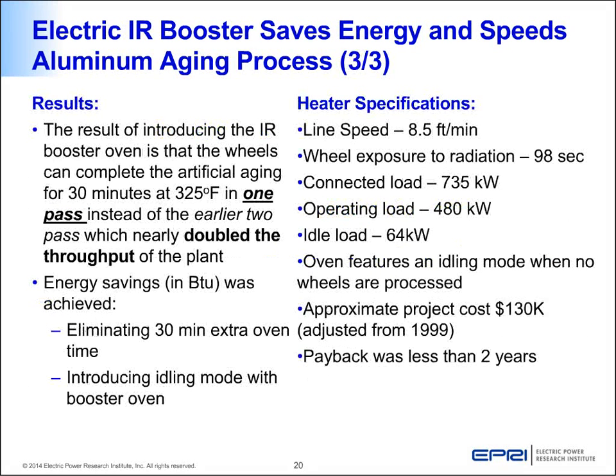So this has a significant benefit. First, it reduced the bottleneck and increased the productivity by 2 times. That was the first benefit. The second benefit was the energy savings on the natural gas side, where originally there were two passes, now it was cut to one pass. So the energy used for that full pass was saved. And